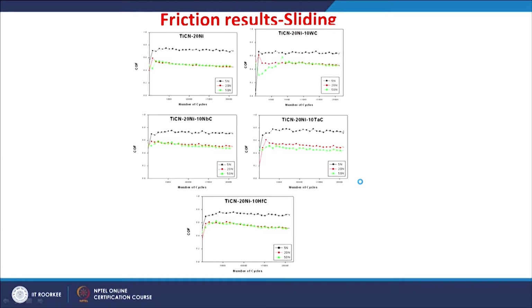Let us understand the results obtained from this study. If you look at the coefficient of friction as a function of number of cycles, more or less similar features can be observed. Initially the coefficient of friction increases to a maximum value within a few hundred cycles, and then it stays at a steady state until the end of the experiment. Generally, the coefficient of friction is maximum in the initial stages because of the running-in period behavior, presumably because of the rubbing action of the asperities. Once these asperities are rubbed against each other, a stable contact forms and that leads to a steady state.